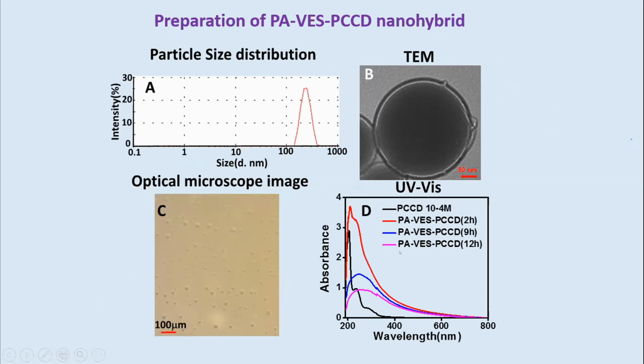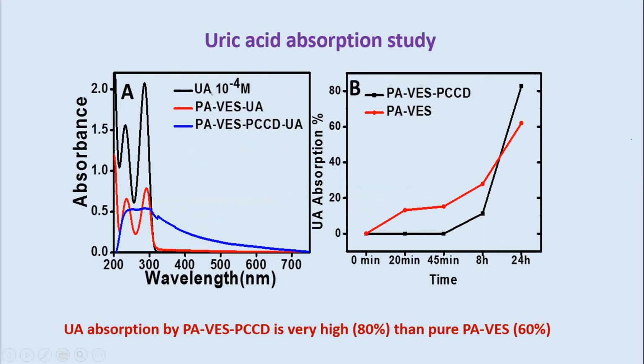I also observed the attachment of my carbon dot to the vesicles by UV-visible spectroscopy, and it was observed that there is a significant amount of attachment to the vesicles. Finally, uric acid absorption at a particular concentration was recorded, and it was observed that around 80% of the uric acid was taken up by the nanocomposite, while only 60% was observed for the pure vesicles.